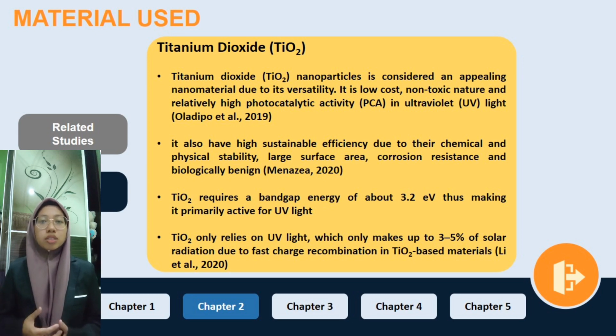It also has a high sustainable efficiency due to its chemical and physical stability, large surface area, corrosion resistance, and being biologically benign. The titanium dioxide requires a band gap energy of about 3.2 electron volt, thus making it primarily active for UV light. Titanium dioxide only relies on UV light, which only makes up 3 to 5% of solar radiation, due to fast charge recombination in titanium dioxide-based material.